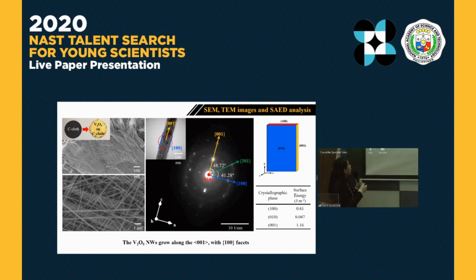we have a fibrous V2O5 that grows along the 001 direction with 010 and 100 planes at its facets. This can be explained by the difference in the surface energy. As you can see, the 100 as well as the 010 plane have lower surface energies compared to that of the 001 plane. Hence, the growth direction will be towards the 001 plane.